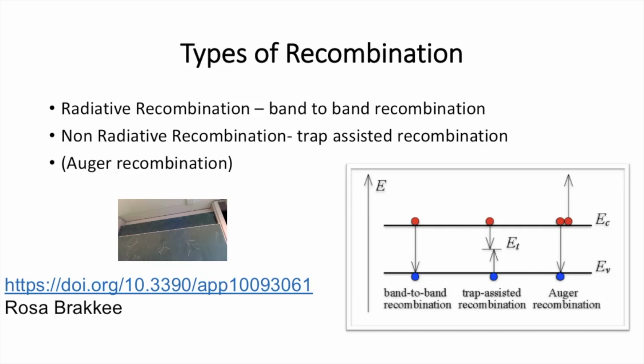So the ideal solar cell, if you put it in a light-emitting diode configuration, then it has an extremely high efficiency, 100% efficiency of light emission. That is the ideal solar cell. And for gallium arsenide, that works like a charm. If you take a gallium arsenide solar cell, which has like 28% efficiency, and you put a current through it, then basically a large amount of the charges you inject are generating emission in the band gap.